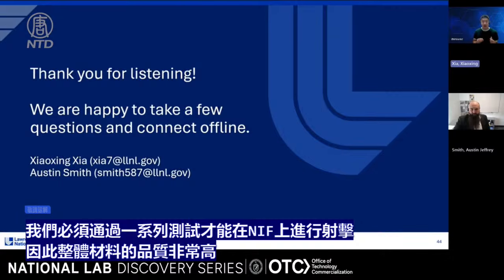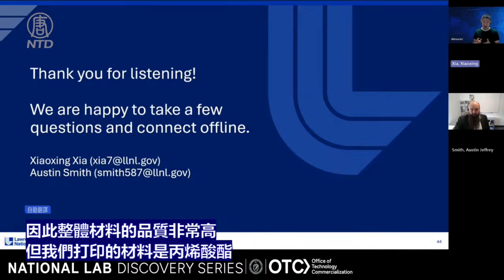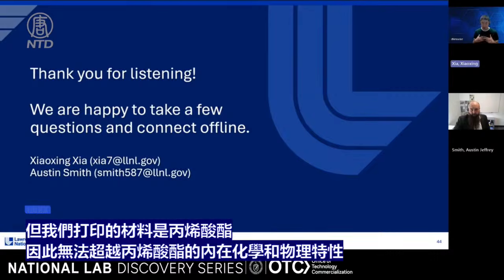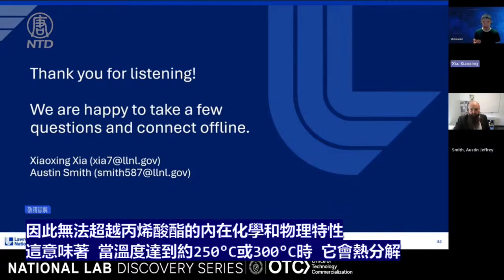So overall, the material is very high quality. The material we print is acrylate, so we cannot do better than the intrinsic chemical and physical properties of acrylate. Meaning that it will thermally decompose when the temperature is above maybe 250 C or 300 C.